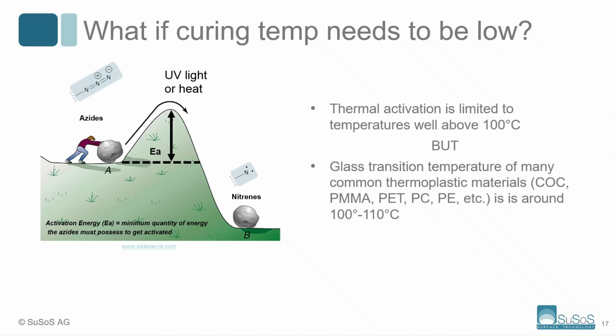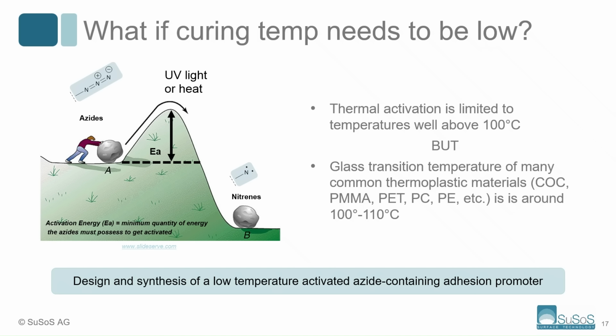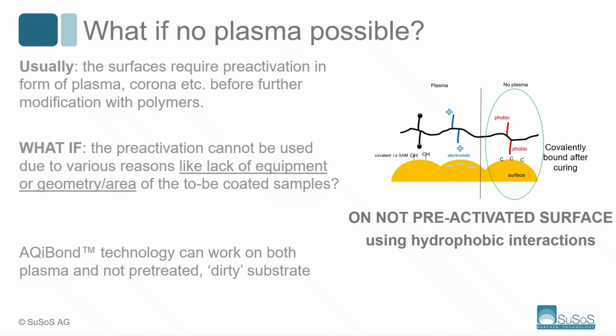But what can we do if we use polymers with a low glass transition temperature, like COC, PMMA, PET, etc., that have a transition temperature at around 100 degrees Celsius, which is below the activation temperature of the azide group on the AQiBond proprietary group? In that case, we designed and synthesized a low temperature, so below or around 90 degrees, activated azide-containing adhesion promoter. It's the second class of AQiBonds. So now we solve the problem of using plastic with a low glass transition temperature.